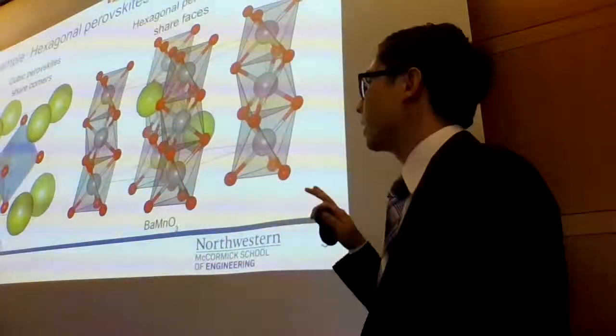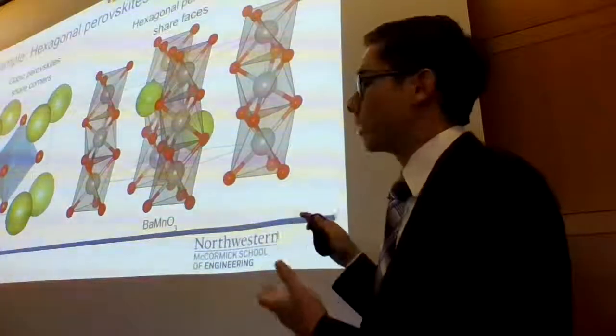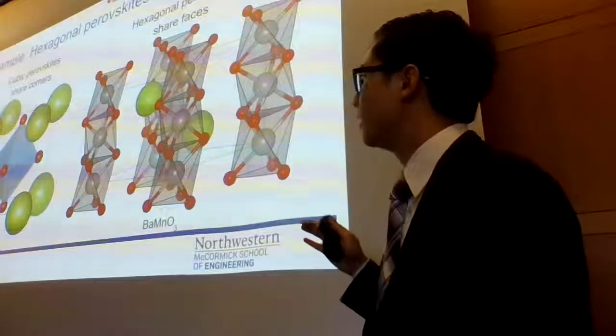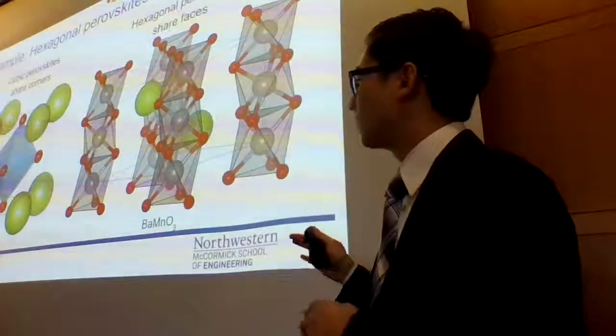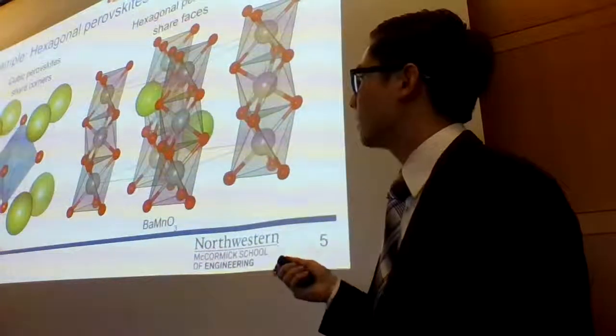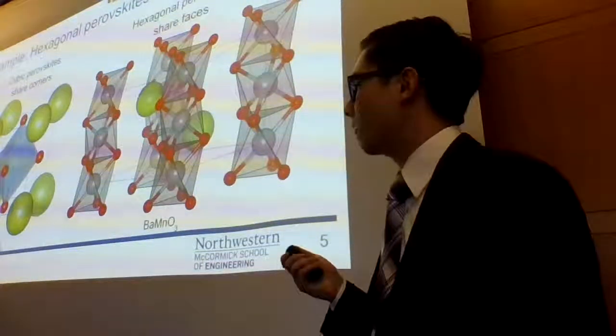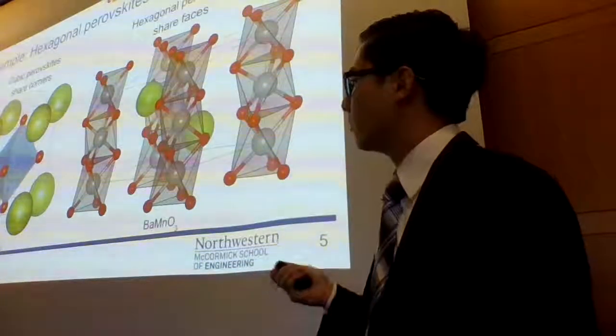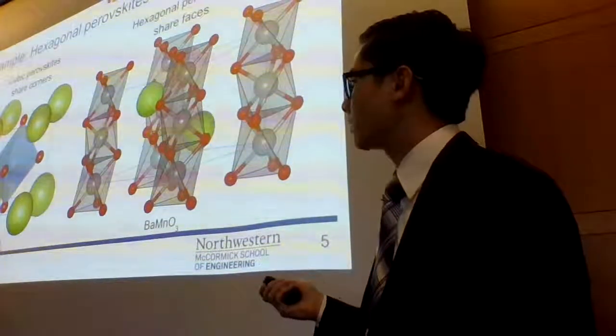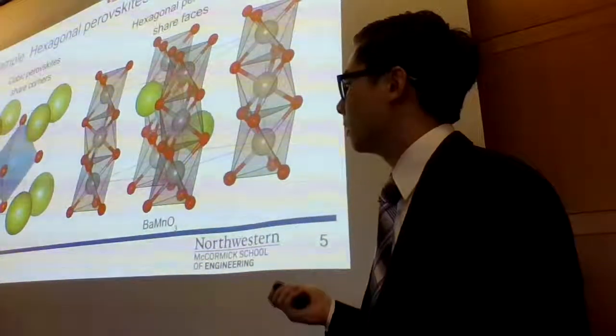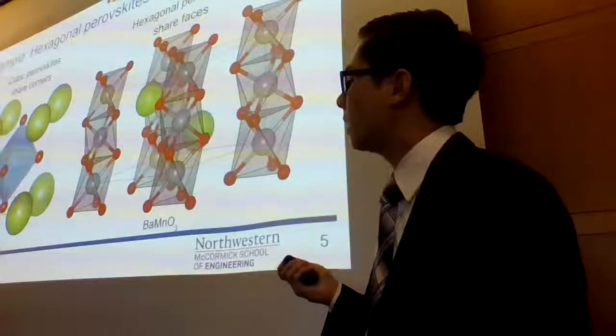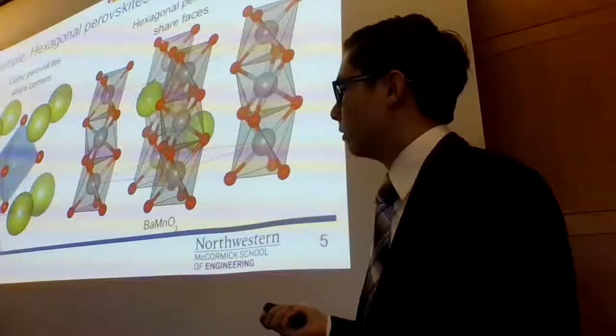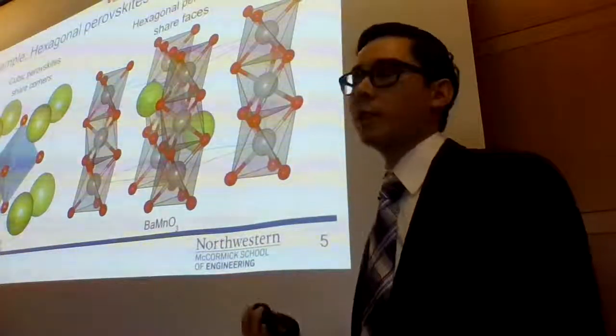In this vein, I actually did an example case study here that I'll talk about using DFT, examining the difference between one commonly studied material, these cubic perovskites, which have an atomic arrangement with these metal O6 octahedra with A-site alkaline earth cations. An example prototypical chemistry would be barium titanate.